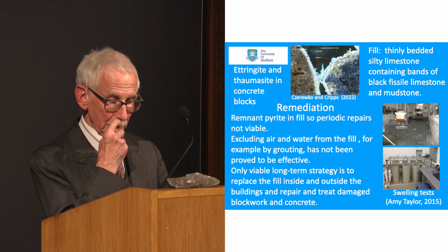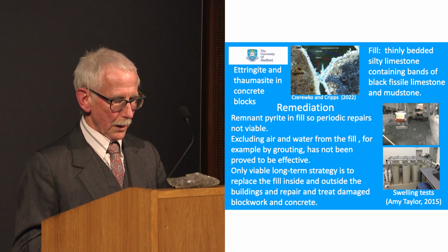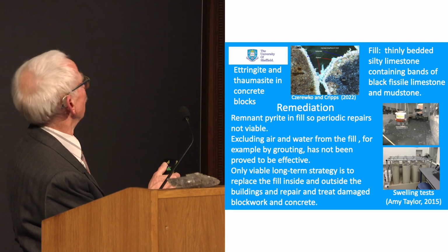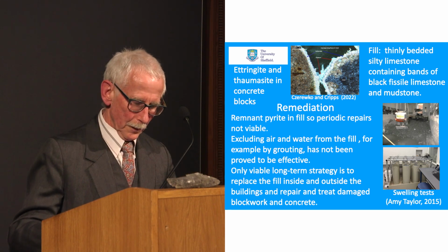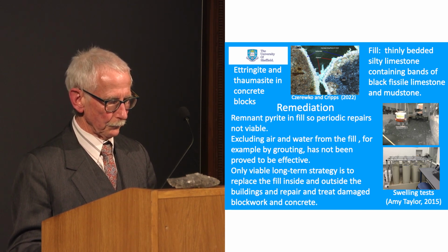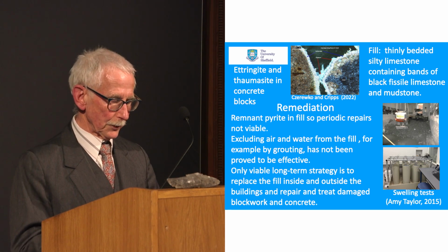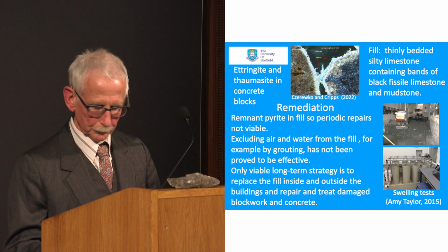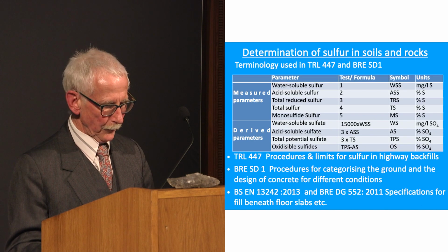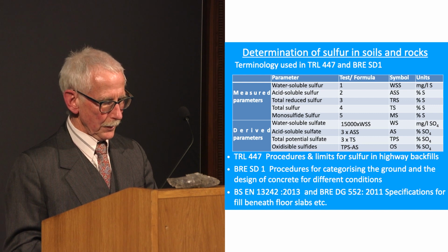Various research studies into the expansion were carried out in Ireland and Sheffield. And this picture here shows the rig used by Amy Taylor for expansion tests in Sheffield. One of the results of this was once the reaction has started, preventing access to water doesn't stop it. I'm now going to talk about the determination of pyrite in soils, and this is where I want to finish the talk.